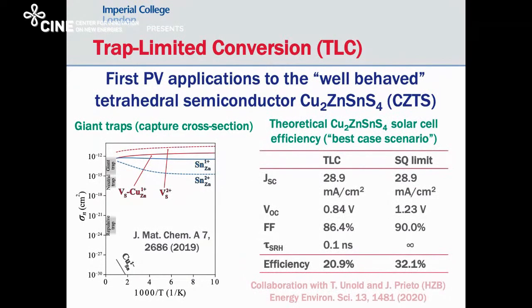The Shockley-Queisser limit just tells you that because you have a certain band gap, you should be able to reach a particular level of performance. So with this material CZTS, Shockley-Queisser will tell you the material should be able to perform at 32% light to electricity conversion. But if we look over all growth conditions at the defects that will form, we can predict using this metric that the best performing CZTS solar cell should have an intrinsic limit of about 21%. So there's about a 10% loss just due to the fact that certain defects are unavoidable in the crystals.